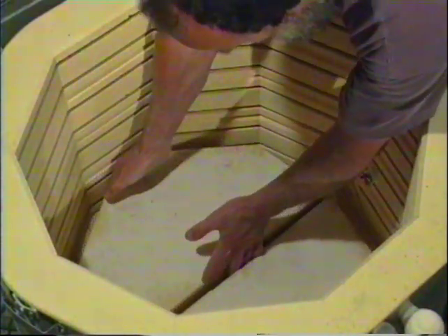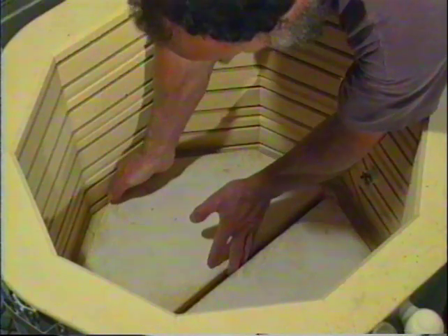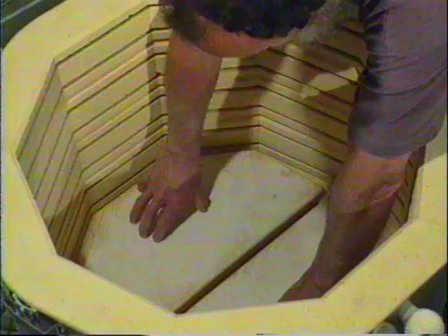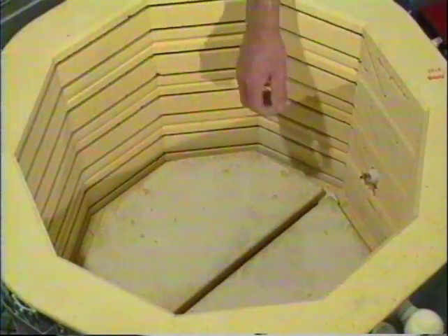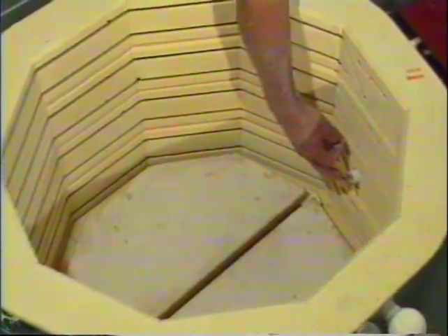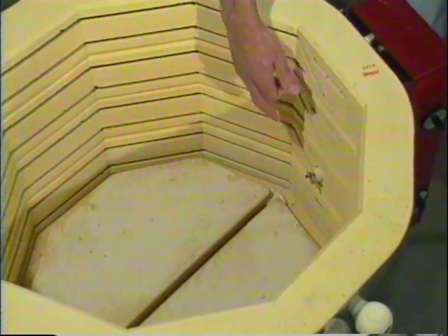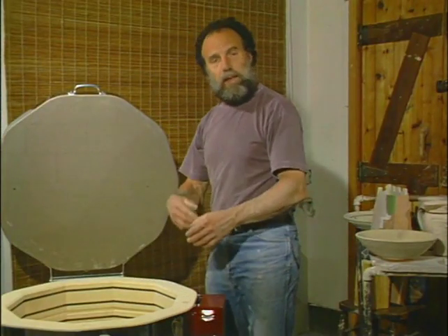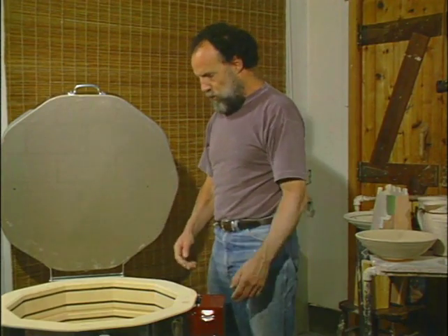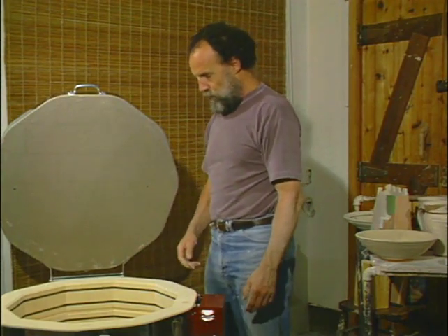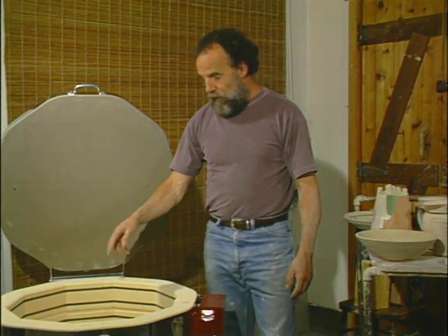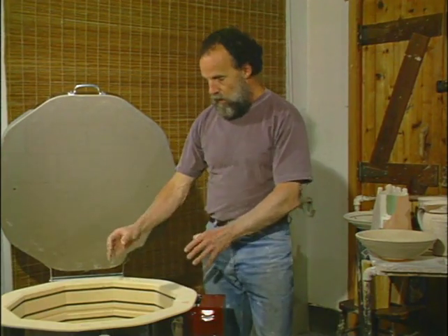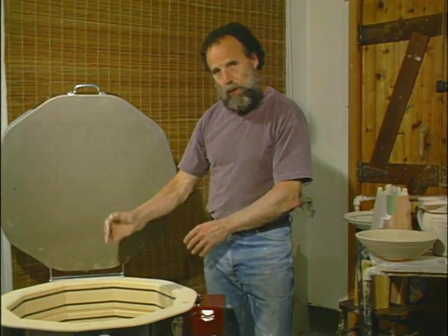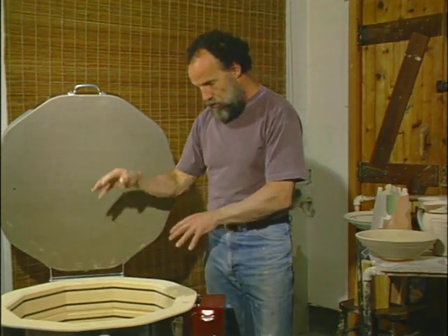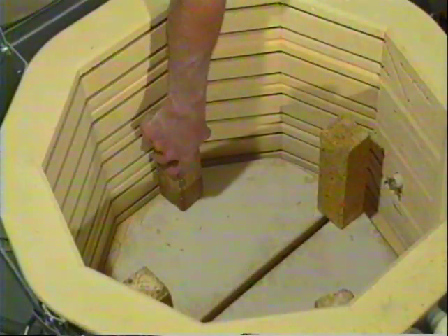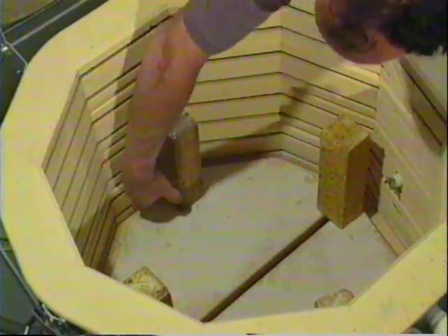I'm starting the stack with a shelf in the bottom, just like we did in the bisque firing. Okay, nice and steady. You'll notice that my kiln sitter small cone is in. That's cone 01, which is a guard cone slightly above the temperature that we'll be firing the glaze firing to. As you stack on now, it's important that the rows of posts stay one above the other vertically, so that the load is transferred down through the same supports into the base of the kiln.